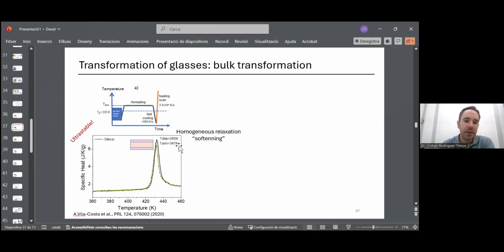We now submit it to, here we say, 347 Kelvin, so above Tg. For some time, we see a shift in the vitrification onset. Okay, so something has changed, but we don't see traces of liquid, because if some liquid has appeared, the devitrification should be here around 380 Kelvin. Okay. So for the moment, we see that the glass has changed a little bit, but no liquid has been